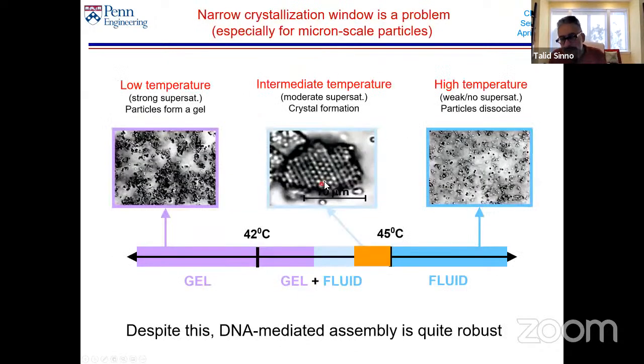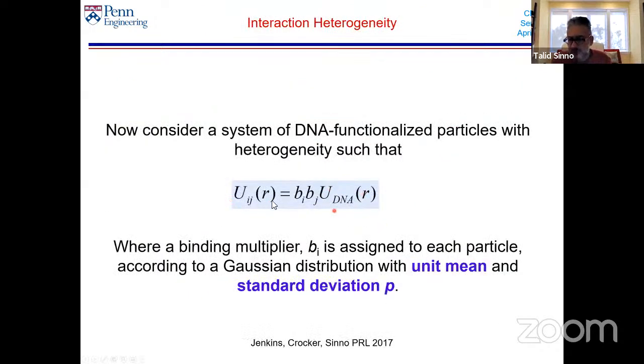I don't have time to tell you how we started thinking about this, but one thing that I didn't mention is that when you make these particles, you're basically putting them in a solution filled with DNA strands, and then the DNA strands become bonded to the surface. The number of strands that bond to each particle is not exactly the same for every particle. There's a heterogeneity there. Particles that have more strands will bind more strongly to other particles, and particles that have fewer strands will bind less strongly. And so instead of every pairwise interaction being the same, there's a distribution of interactions.